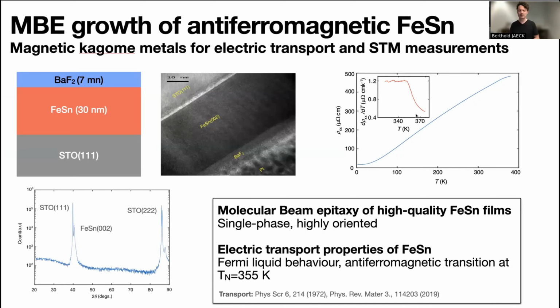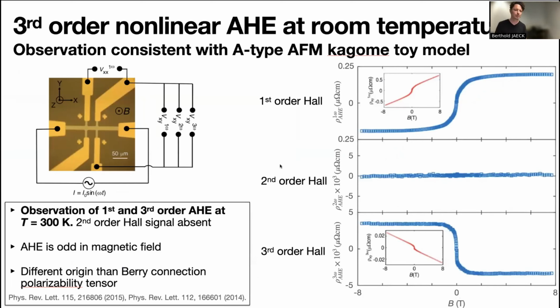What we're interested in now is to see if we can pick up these Berry curvature quadrupole moments when we expose this film to an out-of-plane magnetic field, as predicted by our toy model calculation. To test this prediction, we etched Hall-bar devices and applied a longitudinal AC current drive along the x direction. Then we used lock-in techniques to pick off both the longitudinal resistivity as well as the transverse resistivities at the first, second, and third harmonic.